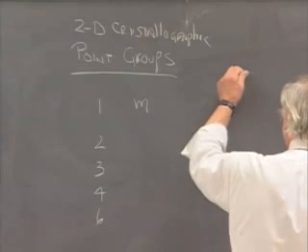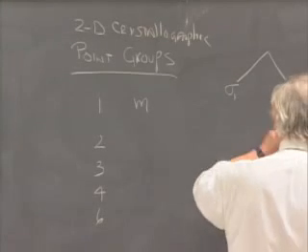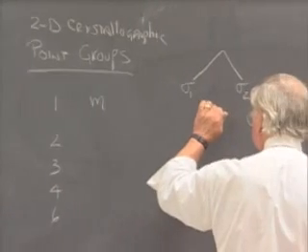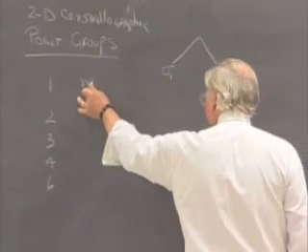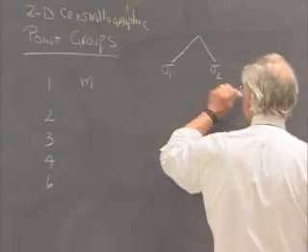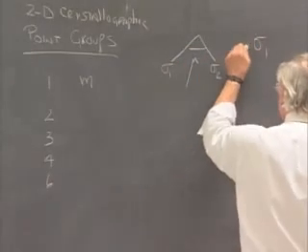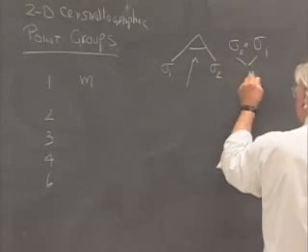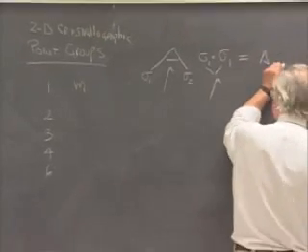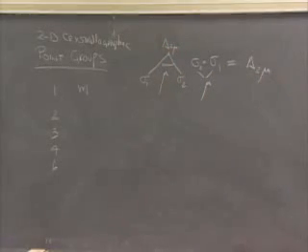In doing so, we used a theorem that said if you take two reflection operations, sigma 1 and sigma 2, and again I use sigma to represent an individual operation of reflection, and a mirror plane is the locus of operations of reflection and then reflecting back again. There are two operations involved. If these are combined at some angle mu, sigma 1 followed by sigma 2, when they are separated by an angle mu, is the same as the net transformation of a rotation about their point of intersection through twice the angle at which the mirror planes are combined.